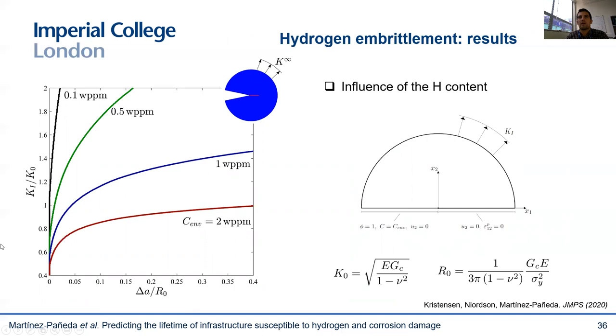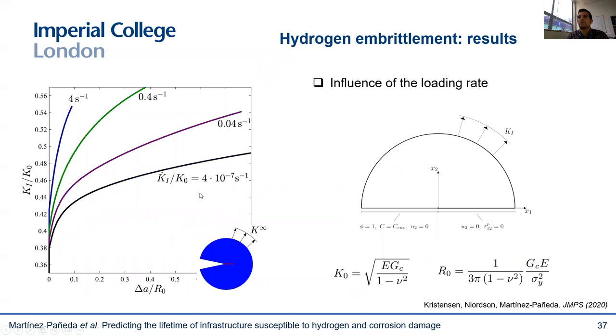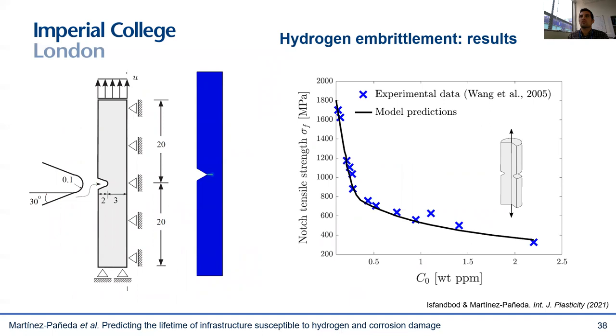Here are some representative results from this multi-physics phase-field-based model for hydrogen embrittlement. These are R-curves — crack growth resistance curves — where applied K is shown on the y-axis and crack extension on the x-axis. In agreement with expectations, the higher the hydrogen content, the smaller the fracture resistance. Results for different loading rates show that the faster the loading rate, the less time hydrogen has to reach the fracture process zone, and thus the higher the crack growth resistance.